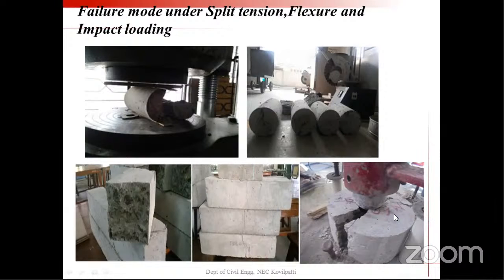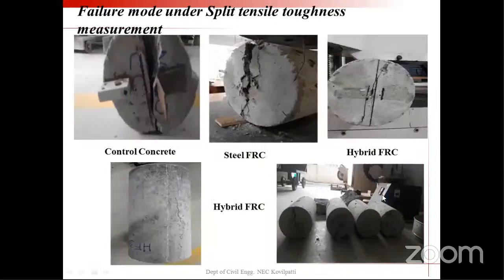And this is during the time of impact testing, ultimate failure. We made the specimen undergo ultimate failure, so this type of observation has been made. And this is during the energy absorption test. And this is control concrete. You can see the entire specimen has been split into 2 pieces. And in steel fiber, you can see the stitching of fibers across the cracks. Still, the failure is very slow and gradual, and it is not a brittle failure.